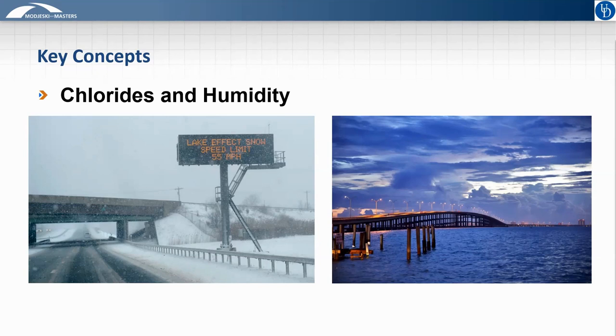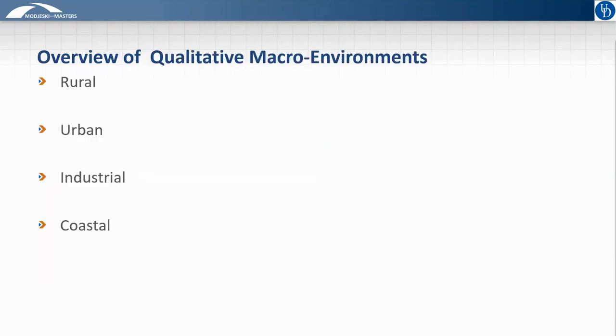de-icing agents can affect that bridge from two sources, either from leaking joints on the roadway above, which Tom will talk about mitigating in a few minutes, or from being dissolved into the snow melt on the roadway beneath the structure, and then that liquid being dispersed and sprayed onto the bridge from the traffic traveling underneath it. So both of those are considerations we need to keep in mind as we move forward.